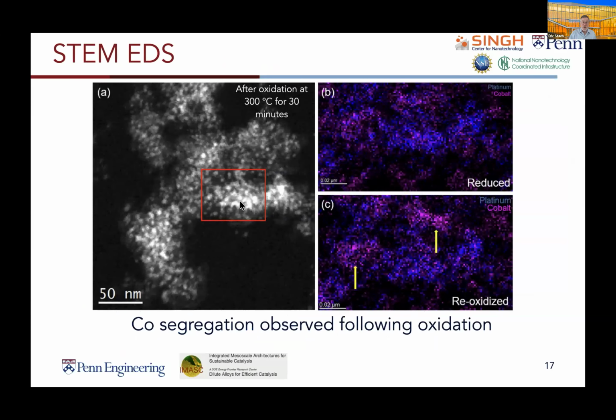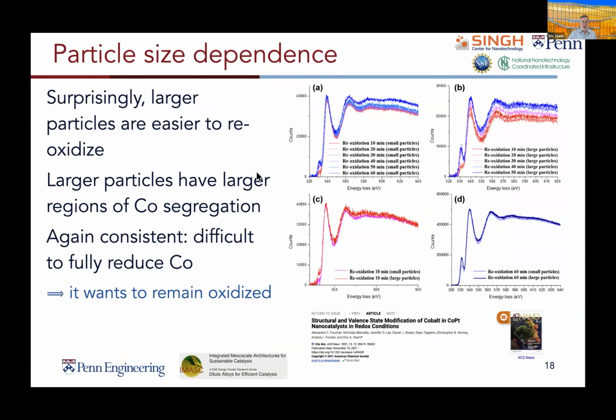Furthermore, if we look at this after the oxidation stage, we see again cobalt segregation to the Co3O4, evidenced in the energy dispersive X-ray spectroscopy. And also, by looking at the electron energy loss spectroscopy, it was a bit of a surprise, but it turned out that the larger particles were the ones that were easier to reoxidize. And those are the ones that also have larger regions of Co3O4 segregation. So all of this is interesting because we're able to see that it's consistent throughout. It's difficult to fully reduce the cobalt in these cobalt platinum particles. And as you expose them to an oxygen environment, they undergo a transition to a different outer surface oxide phase. So this is a paper here, if you're interested, describing all of this.